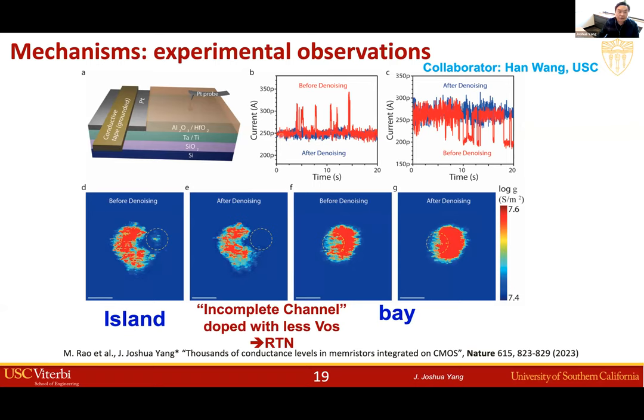And then we use a voltage that is smaller than its switching threshold voltage, but larger than the normal reading voltage, to denoise it. In this case, we use the voltage polarity that normally would switch the device off, but with a relatively small voltage applied to the device, it can be denoised. And as you can see, after denoising, the blue curve shows stable resistance levels, and the conducting AFM shows that this island is gone.